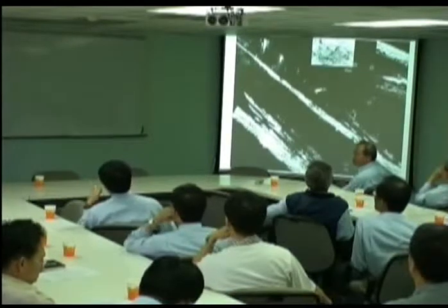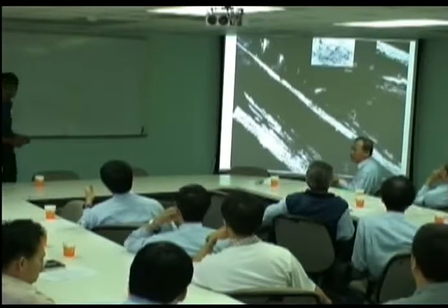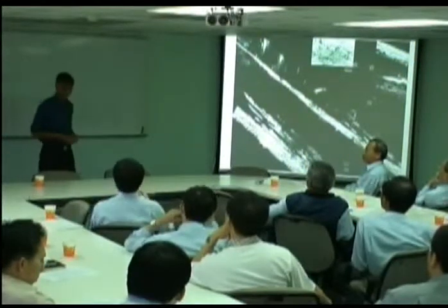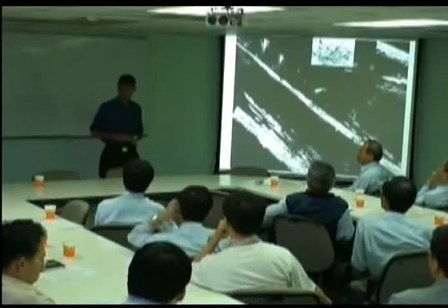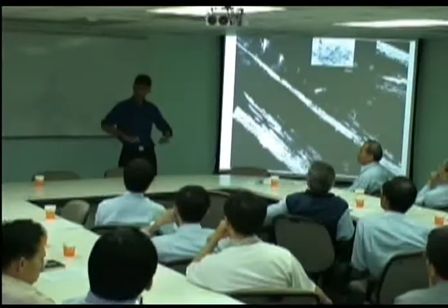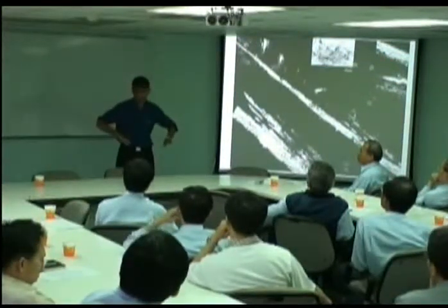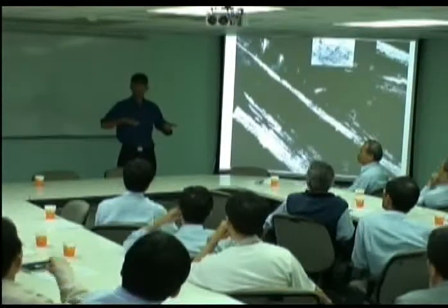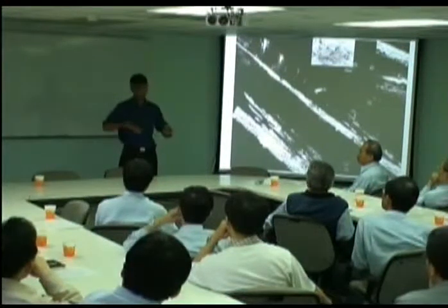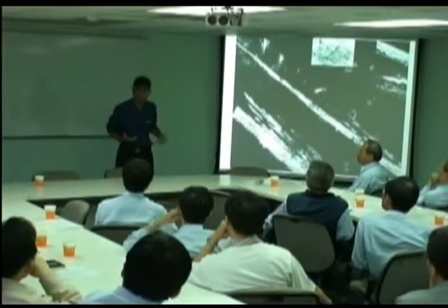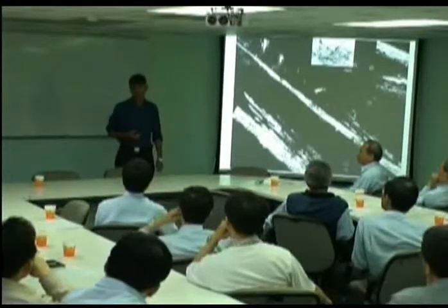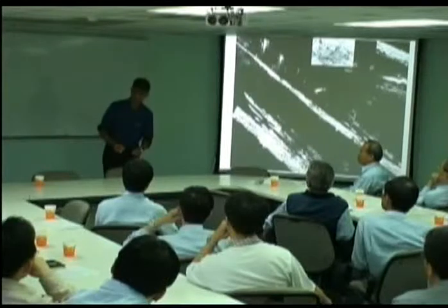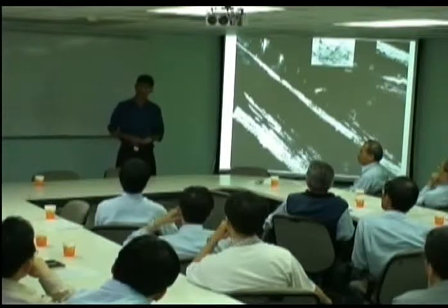So why does martensite not have this kind of thing? That's right. So it's a very good question. The reason is it's a lower temperature and the austenite is stronger. Now, supposing that you make martensite at a high temperature, by making the MS temperature high, you get exactly the same. Or if you deform the austenite and then form martensite, again it will stop growing.